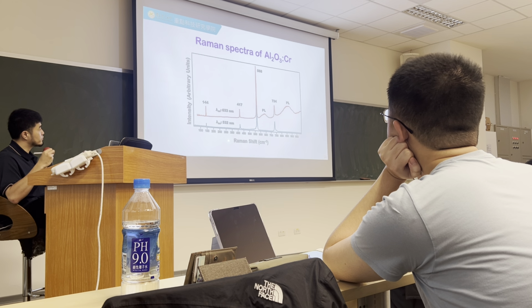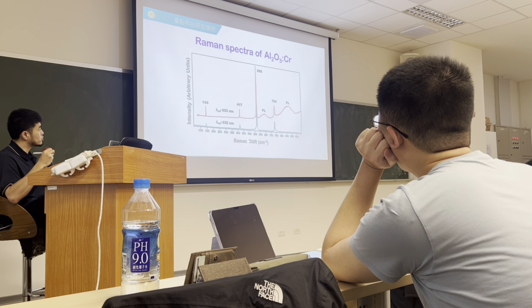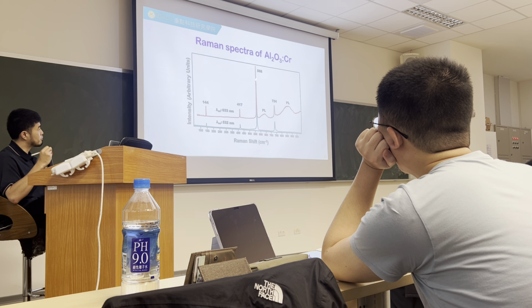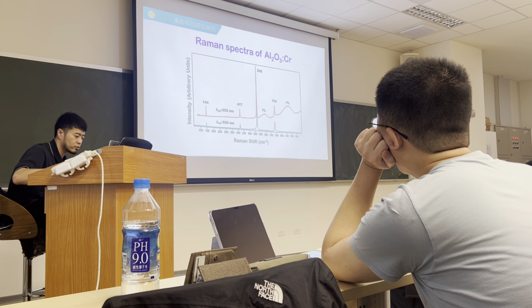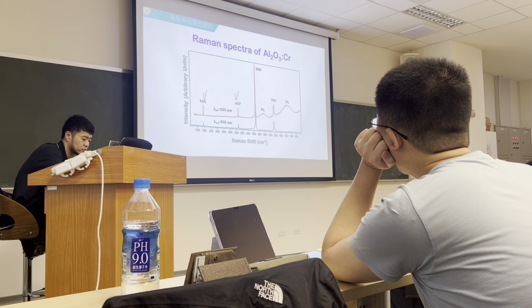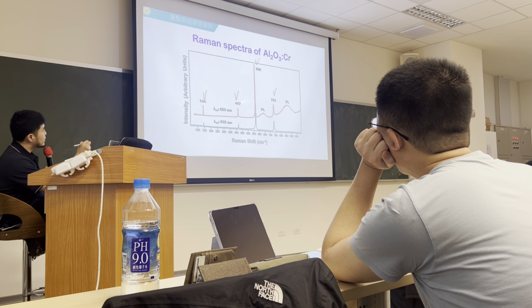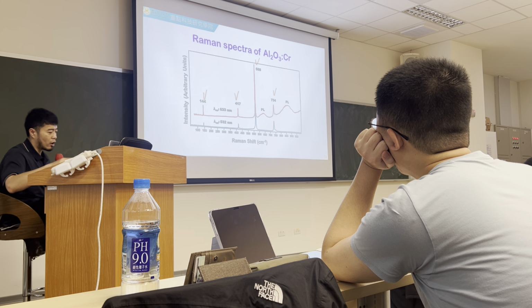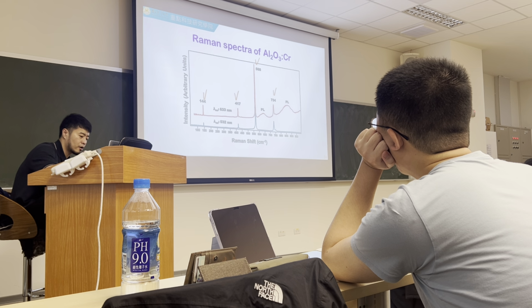In the Raman shift plot, as I mentioned, if the peaks are aligned pretty well, those should be the Raman signal. But if one appears sometimes over here, and whenever you change to another excitation you cannot see it, you are pretty sure those are the fluorescence.